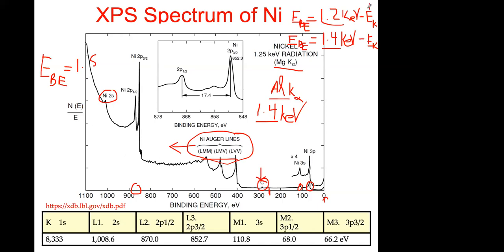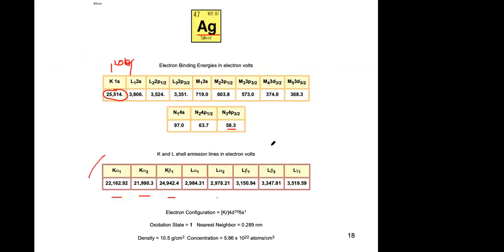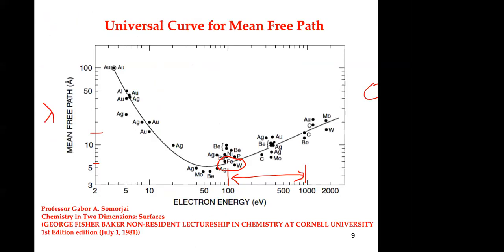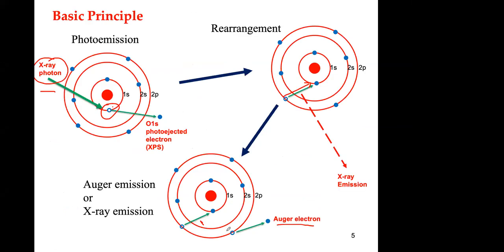The kinetic energy of the Auger is constant because it depends only on the transition. For example, this Auger depends on this transition. This energy difference is used to remove this electron, so the kinetic energy of this Auger electron is the same. It doesn't depend on the energy of the photon. So that's not going to change.